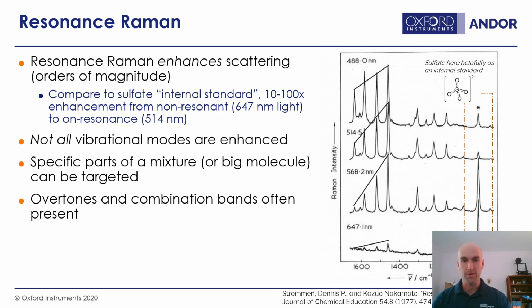So you're looking at a mixture of A, B, and C, and we were talking about before, that's one of the complexities of Raman spectroscopy, where you'll get potentially overlapping spectra weighted by how much of A and B and C are in there. But now we can just light up A, we can light up B, we can light up C, assuming that we have the ability to generate light that interacts on resonance with those components, and those species present have different absorption spectra.